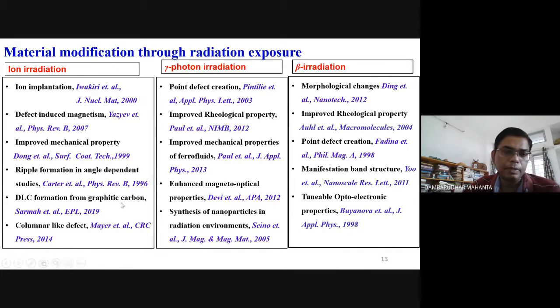Then this is a recent paper by our group. It is about diamond-like carbon formation from graphitic carbon. So this graphitic carbon is nothing but we just simply took one pencil, HB pencil. Of course, it was a 6B pencil, and it was irradiated. Angle-dependent irradiation was considered. In that case, we found that diamond-like carbon can be formed. Similarly, you have columnar-like defects, left-hand side. The right-hand side, you have point defect creation.